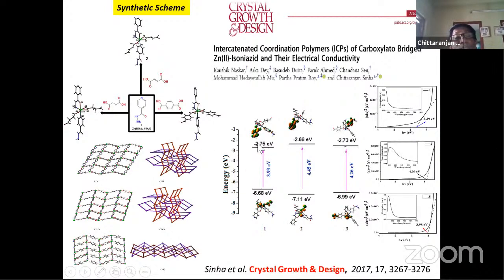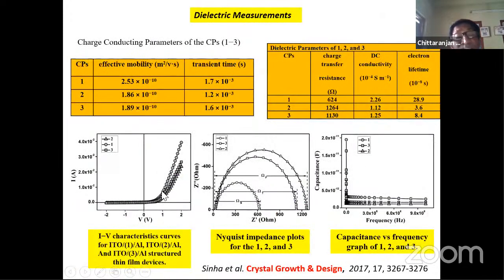And among the bridging carboxylates, the succinate derivative shows the better conductivity since its band gap is the lowest amongst the three. And this shows in the change in the current voltage diagram, in the dark phase as well as in the light phase. This is for the light phase, while this is for the dark phase. Light phase conductivity and the effective mobility, all these things are shown here. And we have three molecules. One is the succinic, second is the fumaric, and third is the benzene dicarboxylic acid. The charge transfer resistance is the lowest in the succinate derivative. And that is also reflected from the Nyquist plot.